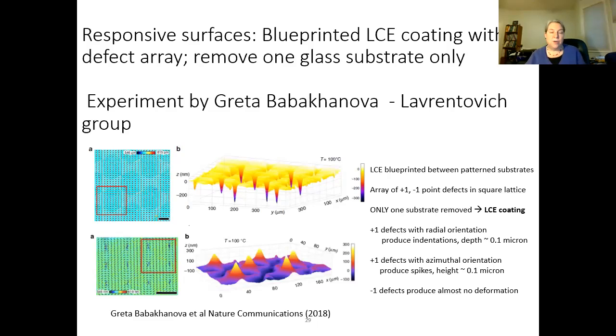Just to give you a quick orientation, one thing she did is she put a network, not just a single topological defect, but a bunch of defects, in a liquid crystal film formed between two pieces of patterned glass. But instead of taking both pieces of glass away, she only takes off one piece of glass, leaving the liquid crystal elastomer as a coating on the other piece of glass. So this material is not going to deform into a bust of President Lincoln. It's just going to have small deformations off the glass because it's attached hard to the glass below. So it has very small displacements, but they are interesting. For instance, when you heat this material, depending on how it's built, it can either have dimples or little spikes.